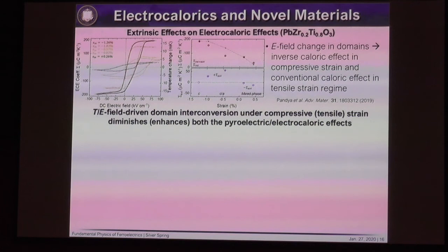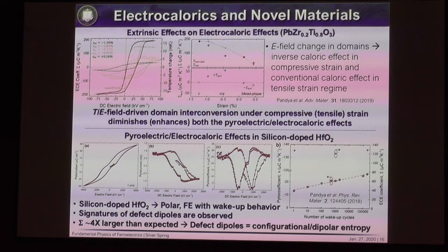We can also look at other types of materials. This morning we had some beautiful talks about the hafnium oxide-based systems. We've also, like everybody else in the world, gotten pieces of these from the Fraunhofer Institute guys and done some measurements there. We see very similar things to what we talked about this morning. We see wake-up behavior in the pyroelectric responses. We see reasonable pyroelectric coefficients for these systems overall. One thing that was interesting here is that if you do this as a function of wake-up cycle, this is the pyro coefficient, that's the red data, we see this wakes up and comes eventually to a level value.